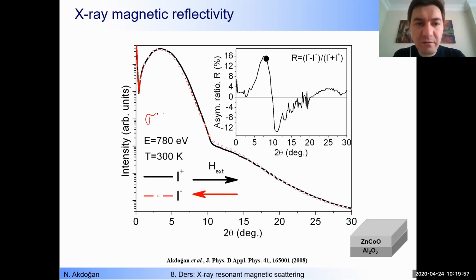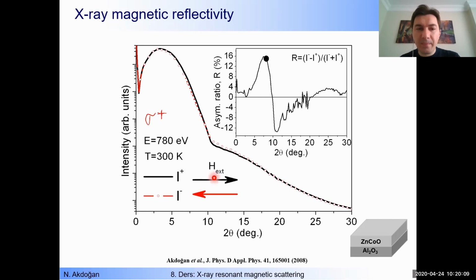Let me write it here. This is right circularly polarized light. And then we apply an external magnetic field in that direction, to the right. Then we take one reflectivity curve as a function of the 2 theta angle. And we reverse the direction of the magnetic field and we measure another reflectivity curve. And we record the intensities for both measurements, okay? So what do you see here? Is there any difference between the reflectivity curves? You can see some differences here, but not so much, right? They look the same.